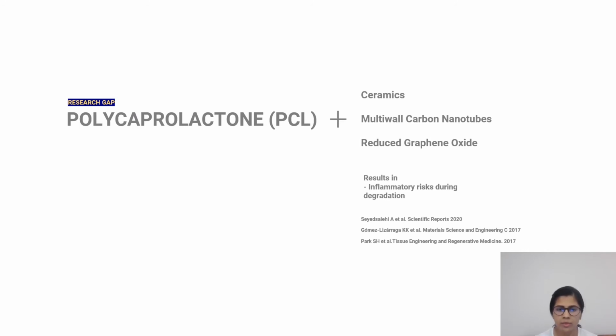At the same time, the most important point, note down here, is that when PCL degrades, it creates an acidic pH environment during the biodegradation process. But none of these materials actually helps to neutralize this pH. There is a huge set of literature showing silk actually helps to neutralize the pH.